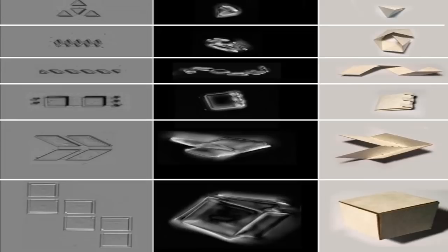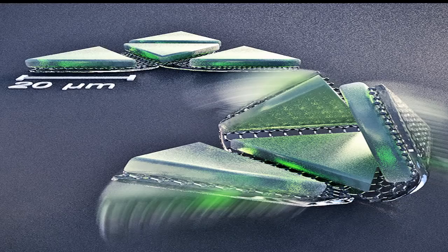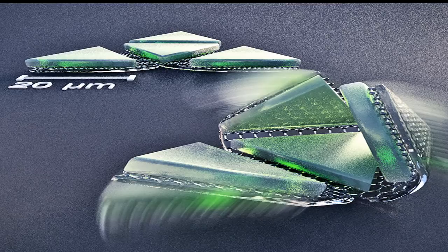It's a neat trick because it's something you can do only with these nanoscale systems. The bimorph is built using atomic layer deposition, typically painting atomically thin layers of silicon dioxide onto aluminum over a cover slip, then wet transferring a single atom layer of graphene on top of the stack. The result is the thinnest bimorph ever made.